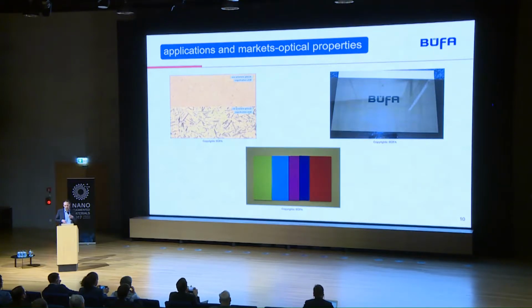These are pictures why we think Tuball has for us new possibilities for the materials. If you use standard materials like carbon black, graphite, you always have a black material or at maximum a dark gray one. And you see in the middle, this is an example of a spray gelcoat. These colors with the Tuball modification are now possible. And this is the new innovative thing.